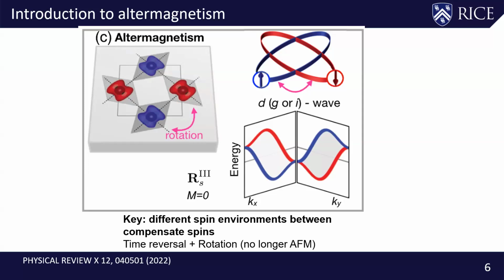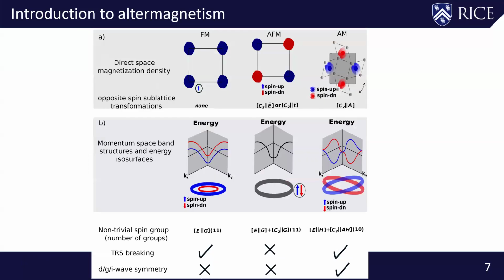Especially if you think about the spin wave, it arises completely from an exchange interaction, in which the exchange coupling only depends on the distance, because the distance between this and this is completely independent of your local environment. Therefore, you should see essentially no difference, in terms of spin waves, as compared with a strictly collinear antiferromagnet.